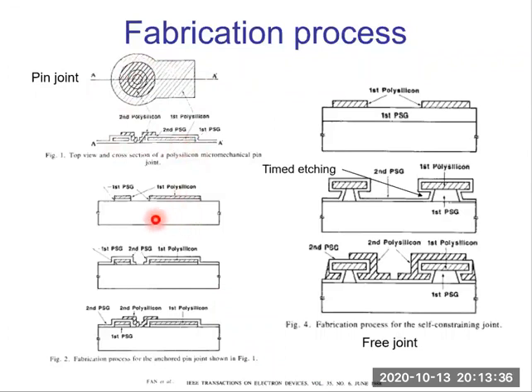So first, we can deposit the first PSG layer and first polysilicon layer. Then pattern this polysilicon layer and the PSG layer. So that's the first step. Then deposit and pattern the second PSG layer. The second PSG layer is deposited and patterned in the step.